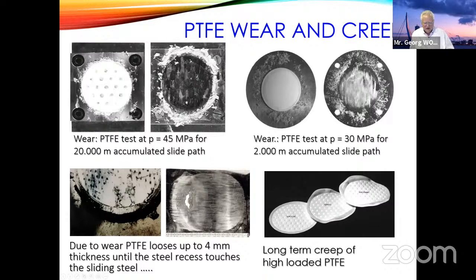The problem is the thickness of the PTFE over the recess is only something like 4 millimeter maximum. And if the 4 millimeter wear away, then it touches steel to steel, and suddenly the resistance to the movement is jumping up. And the problem is it's not very well visible. You really have to inspect quite often to find it. And if the PTFE is overloaded, which can happen very easily due to rotation with eccentrical forces, then you have a long-term creep, which is more or less not stopping. It's like you have a dough for the noodle and you squeeze it and it's going out.